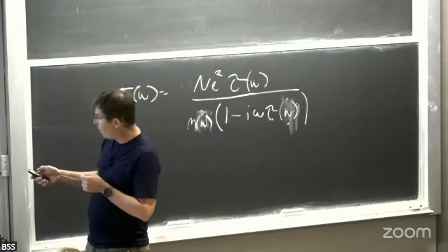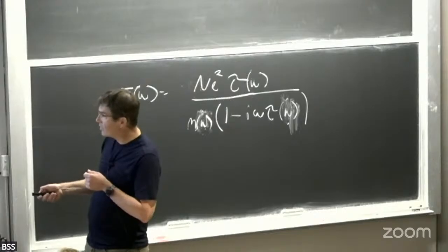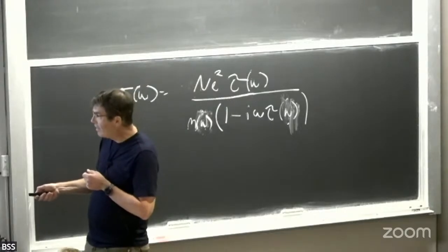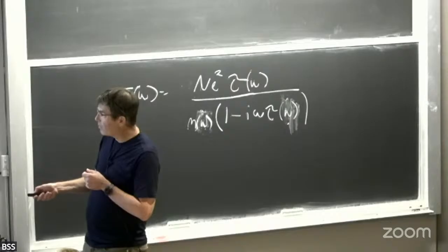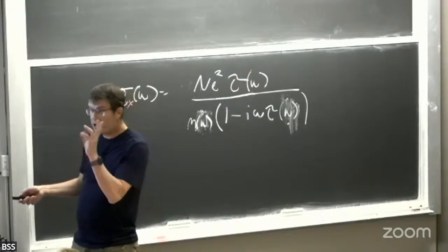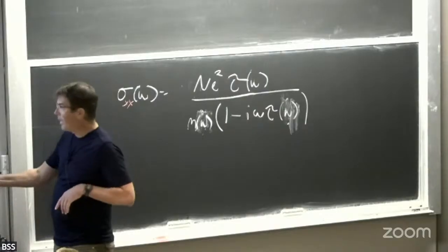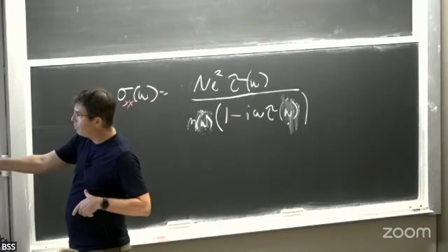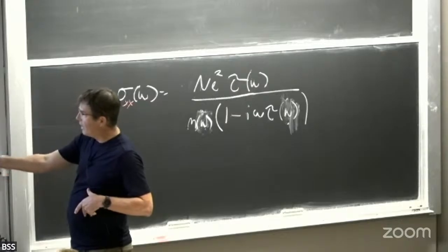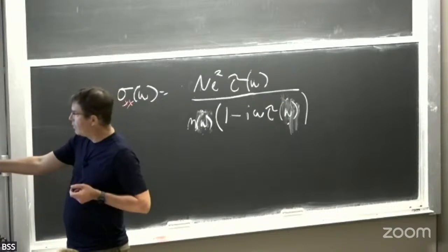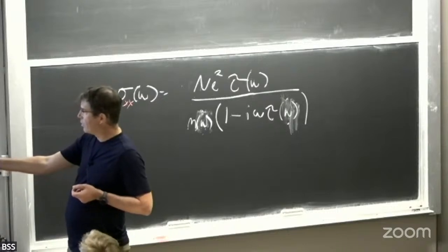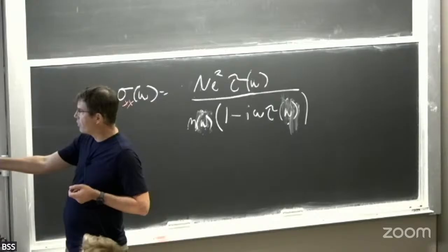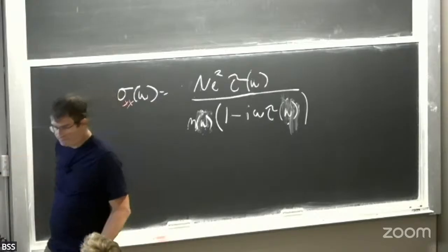And so one basis we find very useful is, you can't really measure this directly in terms of measuring the response to right and left circularly polarized radiation. But we can measure in X and Y, and then we can transform. And the Drude model is a particularly simple form there. It's 0 with no Lorentz force. It's just a Lorentzian centered around zero frequency. And when you put a field on it, it really is just that you displace the zero frequency pole to the cyclotron frequency, and you can just watch that.